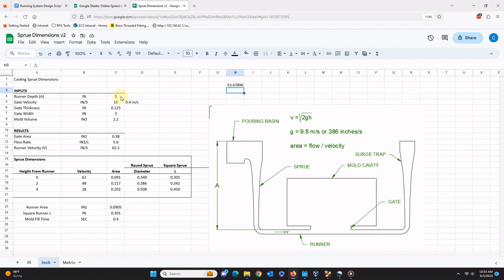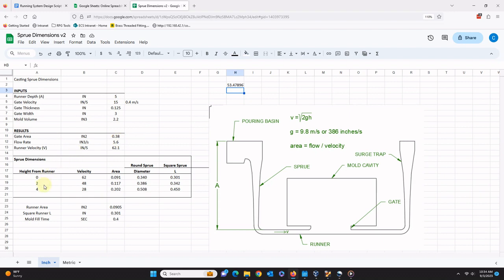Next, we enter the dimensions of the gate into the mold cavity. If the plaque is 5 inches wide and a 3 inch wide gate will keep it away from the filleted corners, the gate is an eighth of an inch thick. This is thinner than the 3 sixteenths thick plaque. As a rule, the gate should be thinner than the object being cast. If the volume of the mold cavity can be calculated or estimated, it should also be entered. Once this is done, the dimensions of the sprue can be calculated for different heights, and the dimensions of the runner will be calculated.